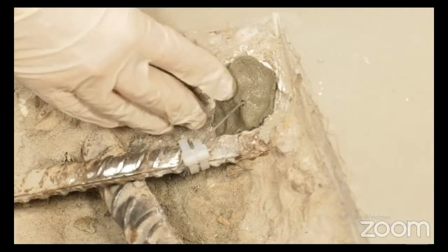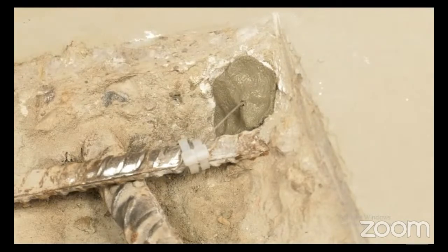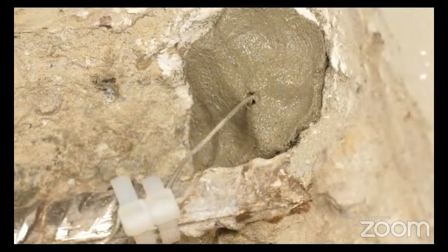A big advantage with patch guard anodes being located in the parent concrete material is that bonding agents and low shrinkage high resistivity repair mortars can be used in the concrete repair areas.